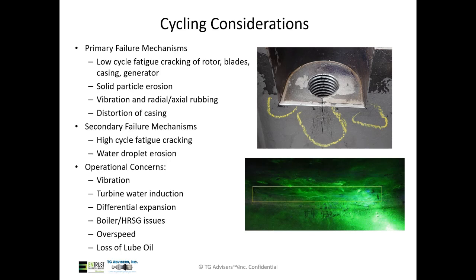On the operations side, we've got to be concerned about vibration. Water induction, that's when we accidentally throw water into an operating steam turbine, can cause quite a bit of distortion. Historically, those have traditionally happened during startups, shutdowns and load changes. I mentioned differential expansion already. We could have boiler or heat recovery steam generator upsets. The risk of overspeed is always elevated, and same with loss of lube oil. So those are operational events that could occur, but for various reasons, they tend to happen more during these transient operating events like startups, shutdowns and load changes.